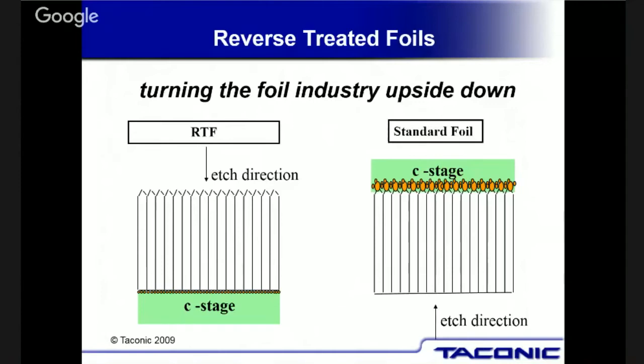But with the reverse treated foils, again, they're smoother. And what we're doing is putting the smooth side against our material. And now when you're etching, you're actually etching through the tooth. And so I look at it and say, it's like calving a glacier. The etching chemistries get right down through the cracks and crevices in the material, and it actually etches away, like they say, like calving a glacier. It actually shears off very straight.